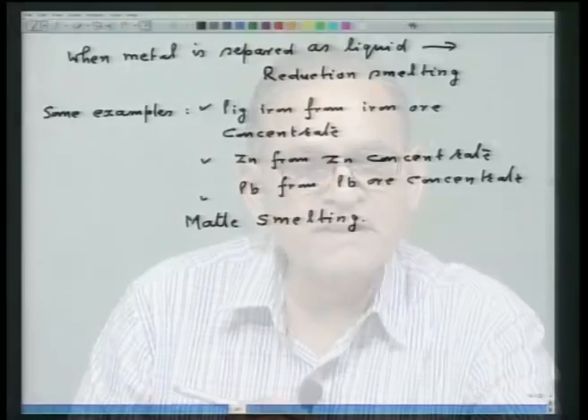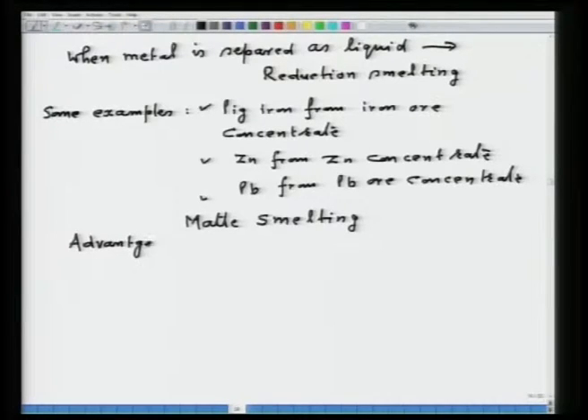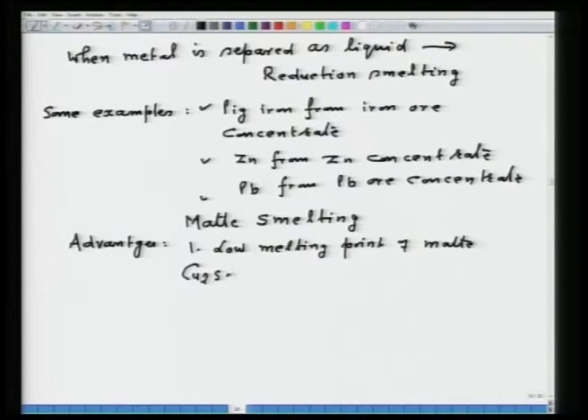Now, obviously, there are certain advantages of extraction of metal through the matte smelting route, because in matte smelting we are separating gangue mineral and producing a matte from the copper ore concentrate. What are the advantages of matte smelting? First of all, the low melting point of matte. For example, Cu2S plus FeS has around 1000 degrees Celsius as its melting point. So, you do not require a very high amount of energy to produce the matte.